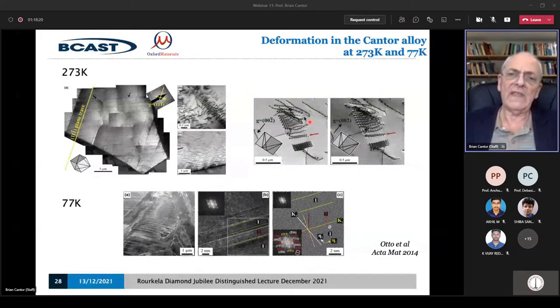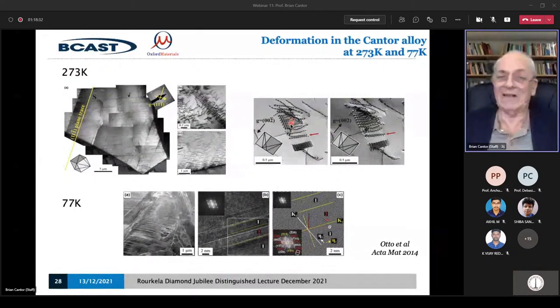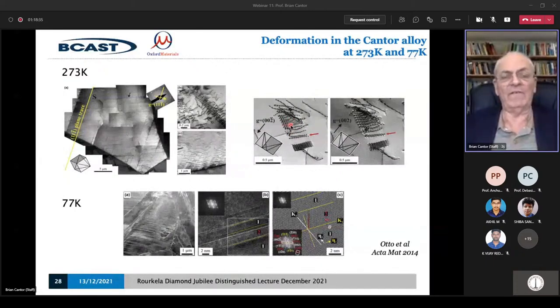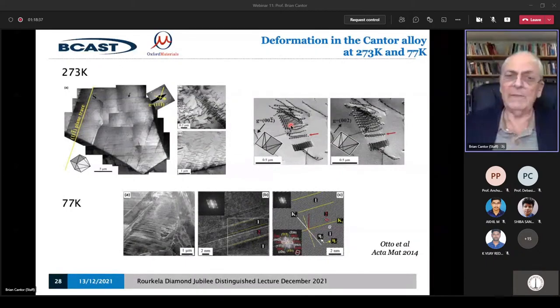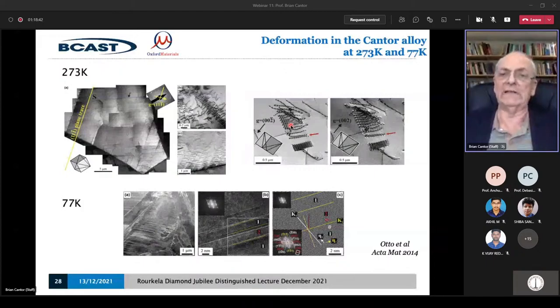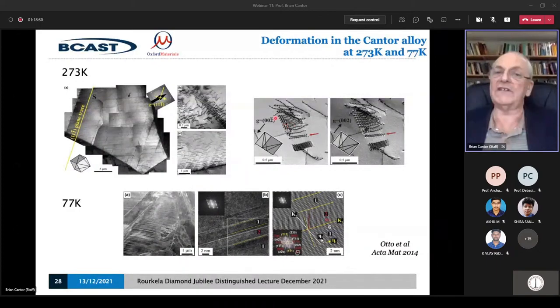Now, this picture is actually from the Cantor alloy, but it would look exactly the same if we looked at pure copper or pure gold or pure aluminium. Exactly the same thing happens. The dislocations move around in exactly the same way. You get the same levels of formability, the ability to shape the material, to turn it into the wonderful shapes of things we want to make. And you also get the same levels of fracture toughness, of resistance to fracture, because it's the local movement of these dislocations that prevents the formation of cracks and their propagation and the fracture of materials.